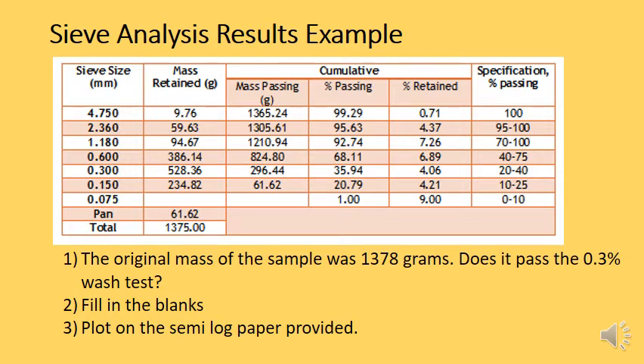Now, following that, we can do a percentage passing. So this is basically the percentage of the 1,375 grams that is smaller than the sieve size. So the 99.29 there, that is the percentage of 1,365.24 over 1,375. That's the percentage passing through. So we can see that 99.29% of all of the aggregate particles are smaller than 4.75 millimeters in diameter. And corresponding to that, we can do the percentage retained, which is basically 100 minus the percentage passing. So only 0.71% of the aggregate is larger than 4.75 millimeter diameter. So that's basically the sieve analysis.